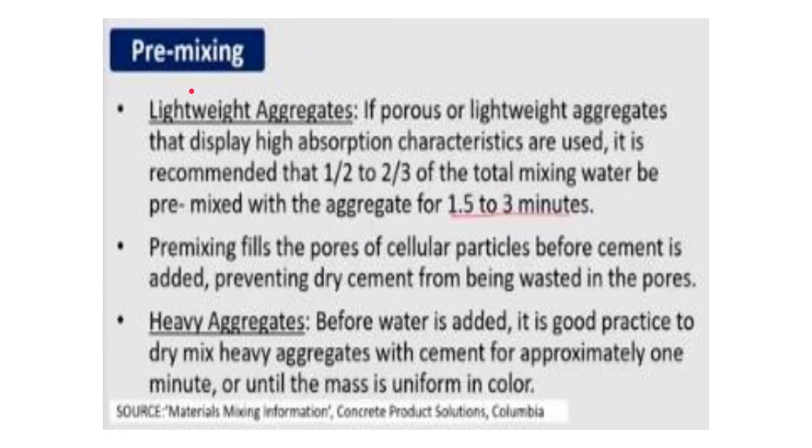Even before mixing, what criteria should be kept in mind? If we go to lightweight aggregates, if porous or lightweight aggregates that display high absorption characteristics are used, it is recommended that 1/2 to 2/3 of the total mixing water should be pre-mixed with the aggregate for 1.5 to 3 minutes. Pre-mixing fills the pores of cellular particles before cement is added, preventing dry cement from being wasted in the pores. So that is one of its uses.